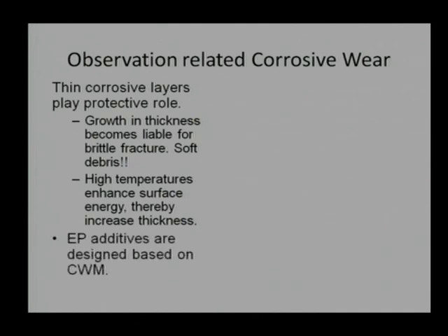One interesting thing is that we use additives in lubricant, and one kind of additive is the extreme pressure additive. Extreme pressure itself is a misnomer, it should be extreme temperature additives. What happens to these additives? When the temperature is increased beyond a certain limit, they turn out to be active and then they react with the surface, but in a controllable fashion. We will make a layer, maybe say 5 micron to 10 micron on the surface, and that will act as a lubricant layer. So, in other words, EP additives can be used for higher temperature applications.